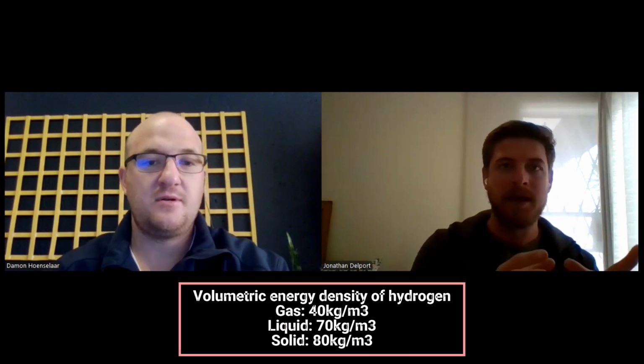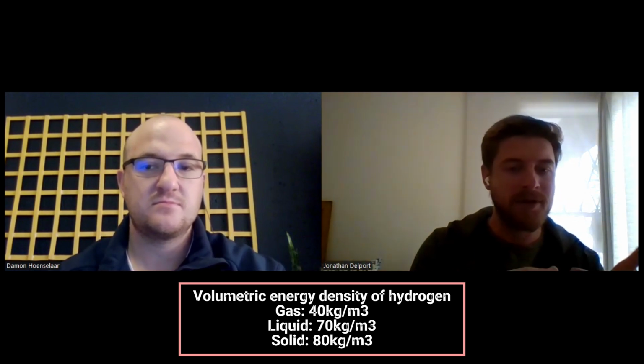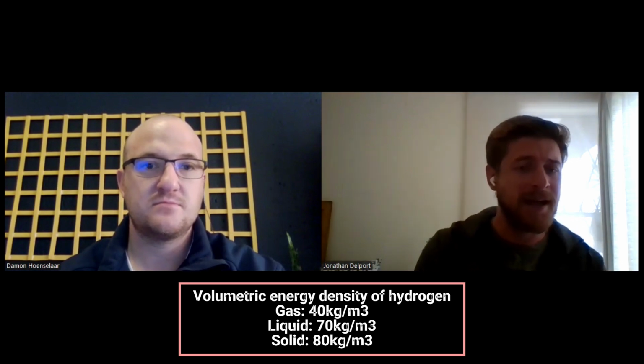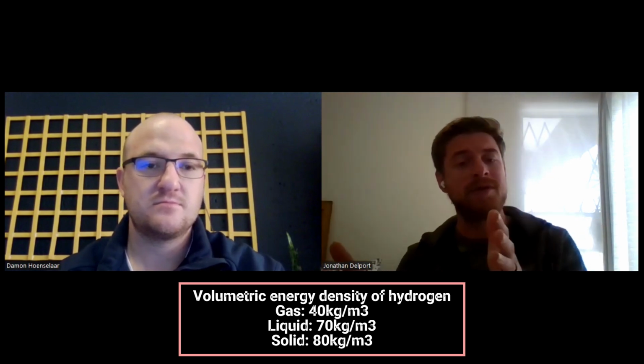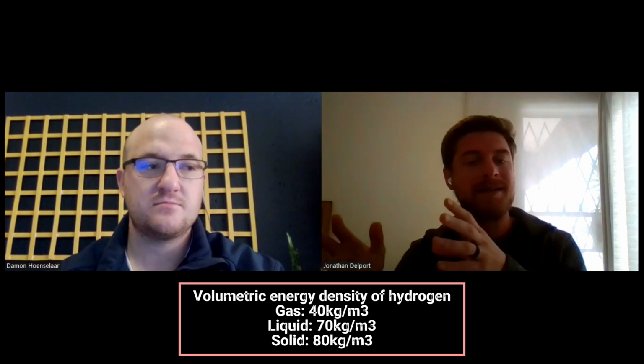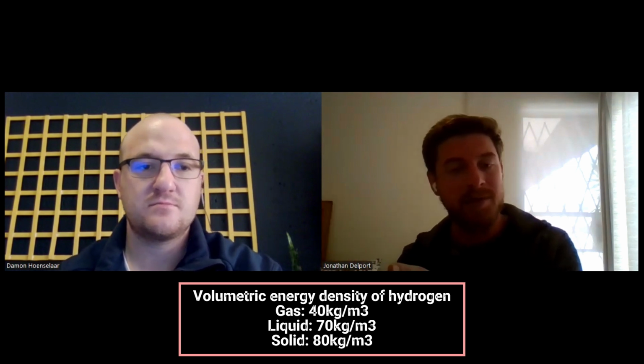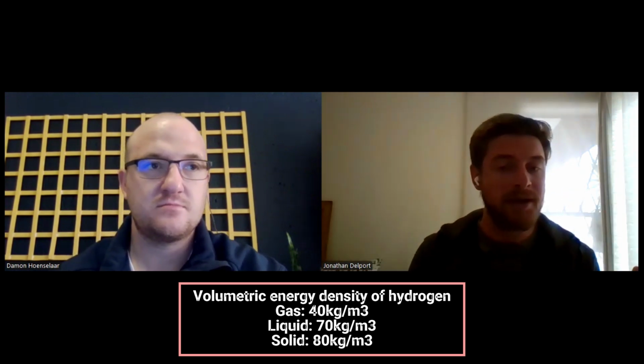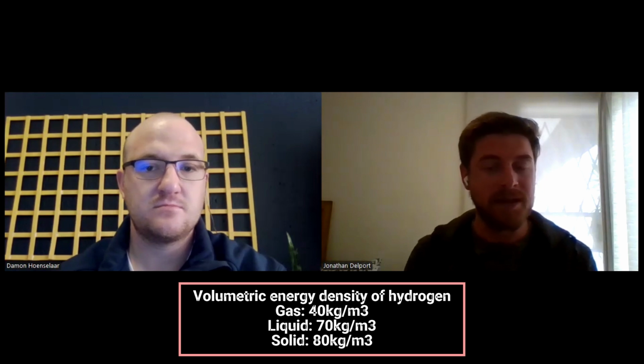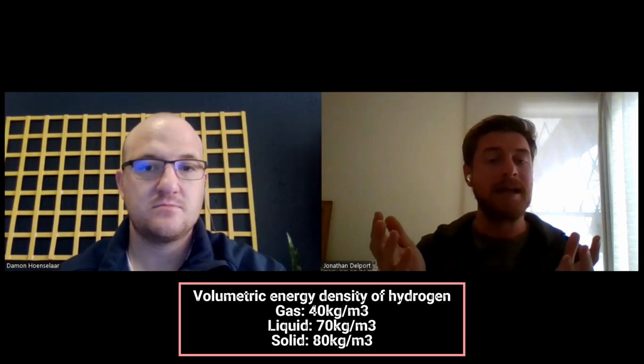No, agreed. And just to sum up on why this is important for hydrogen, like you said, to store it as gas, if we look at it per cubic meter, you'll only get like 40 kilograms of hydrogen per cubic meter as a compressed gas. And that's at 700 bar. Then if you can liquefy it, you'll get about 70 kilograms per cubic meter. But if you can make it into a solid, you get about 80 kilograms per cubic meter. So, it's there.